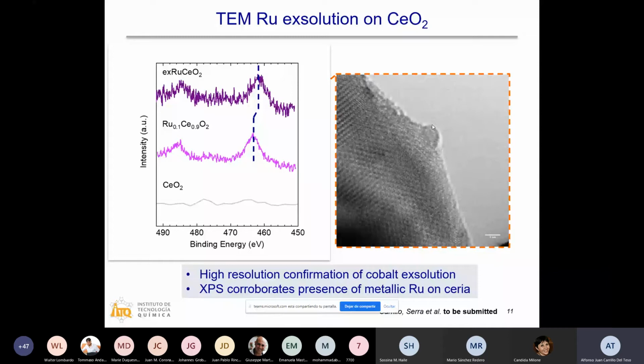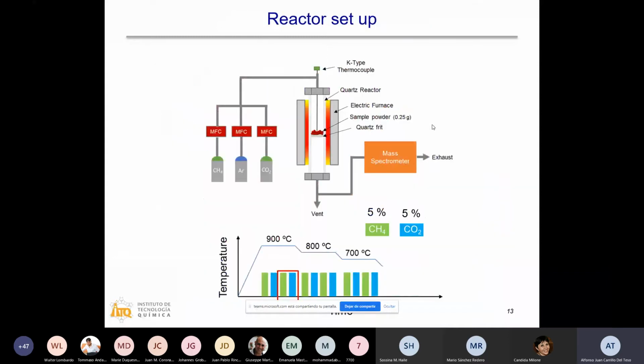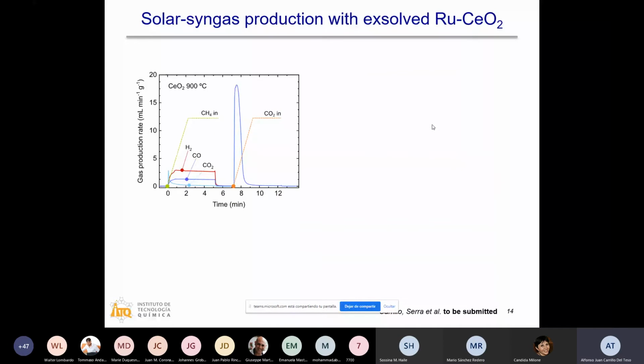The performance was tested in a high temperature reactor. We checked different temperatures. Initial tests were done injecting 5% of methane and then doing CO2 splitting with 5% of CO2. Here I'm showing the gas production profiles for a reduction-oxidation cycle with the ceria at 900 degrees Celsius. When we inject methane, there is the production of CO2 and also the steady, flat production of hydrogen and CO, as was observed previously in the literature. And after we inject CO2 in the reactor, we observe the formation of carbon monoxide.